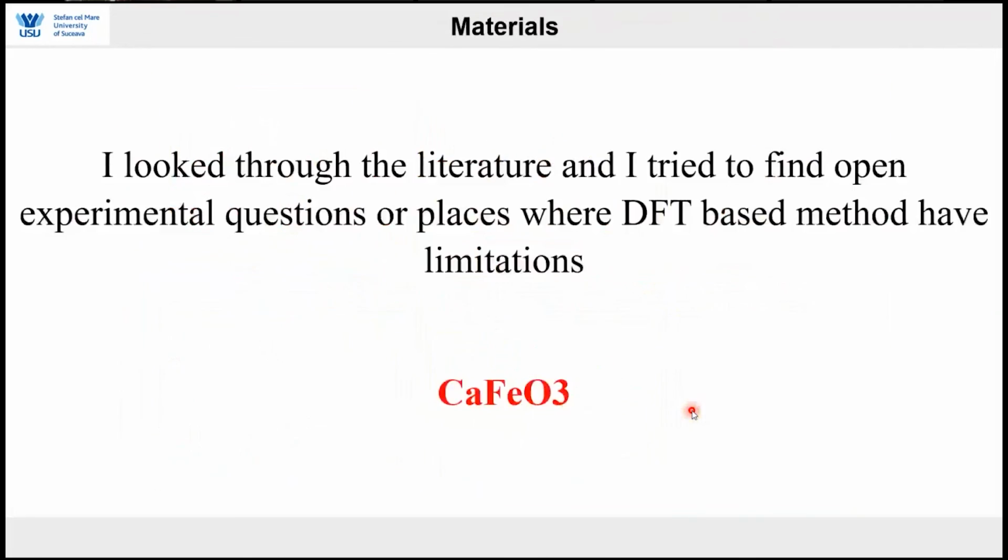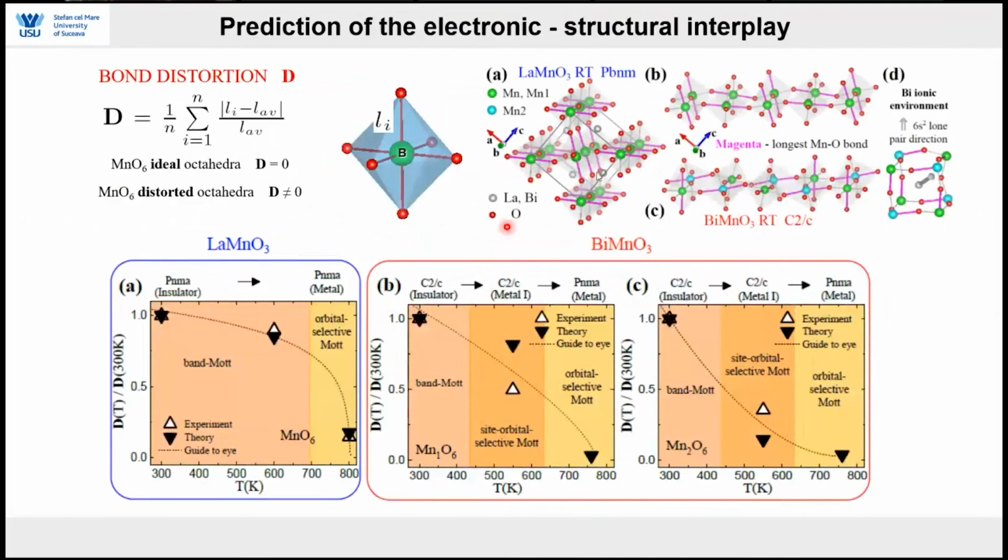Now, what I want to mention here is that for bismuth MnO3, none of the other methods could get the gap. I think there are more than 15 different types of calculations to get the optical gap, and DMFT gets it right from the beginning, from the first calculation, with no tuning, with nothing. So the validation of our method was the fact that the optical gap was properly computed by the method.